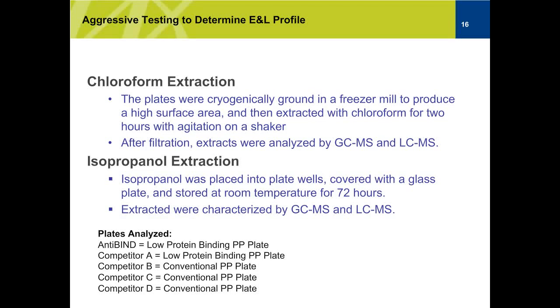The tech note goes into detail on the different experiments that we have done, but what we tried to do is perform very aggressive testing to determine the extractables and leachables profile for all of these plates and compare them to Anti-Bind. So we did a chloroform extraction. We took the plates, cryogenically ground them in a freezer mill to produce a high surface area, and then let them incubate in chloroform for 2 hours with an agitator and a shaker. After filtration, we analyzed that extract via GCMS and LCMS. I'm just going to show the data for the GCMS, but the full report is available for you to download and check in more detail.